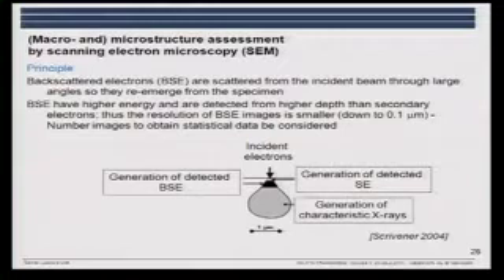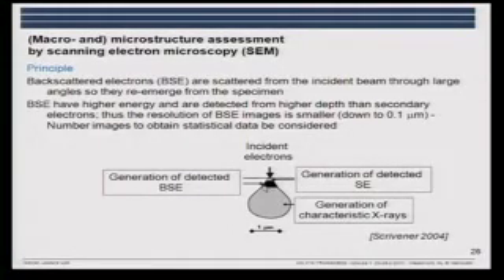Then we can use the scanning electron microscope. And for porosity detection, we use the backscattered electrons. And as you saw on Monday, they are detected from the upper layer, not the same volume as where we detect X-rays from. So here we have the sample, and it would be this area, or the volume, from which we can detect the backscattered electrons. And this is, well, a little less than half a micron in width.